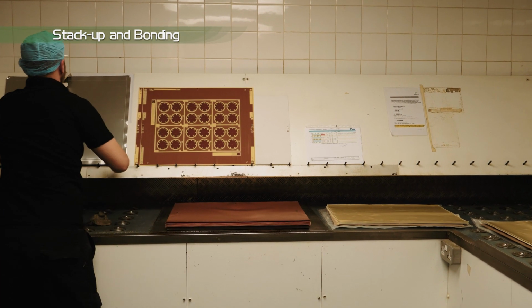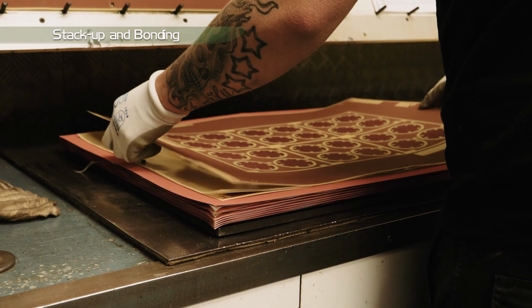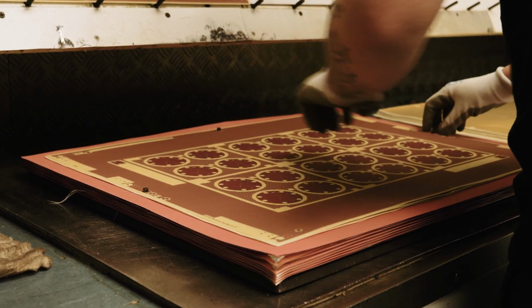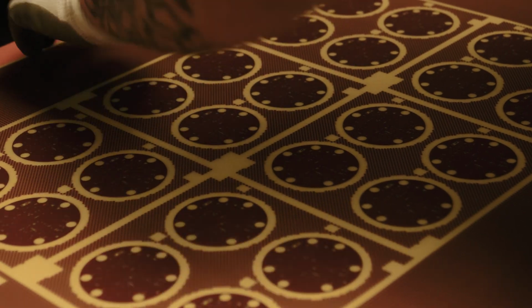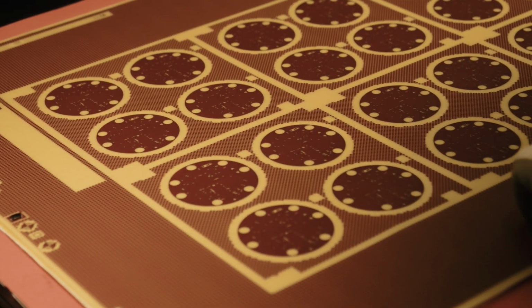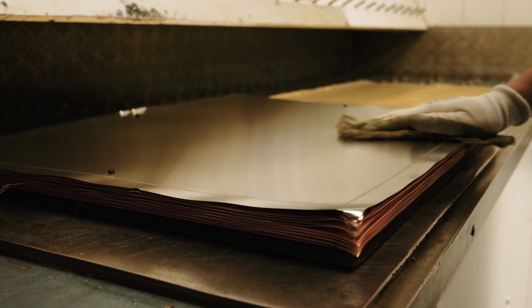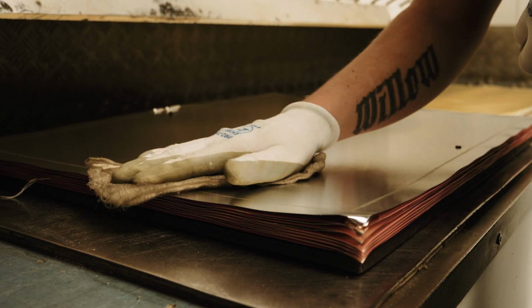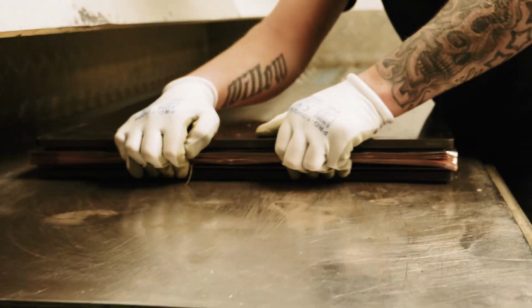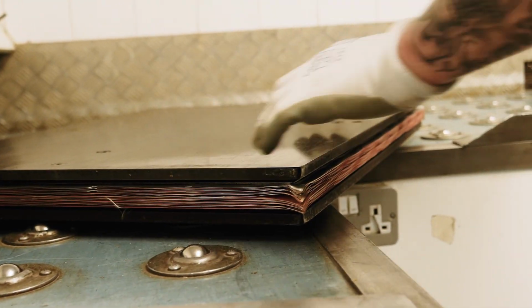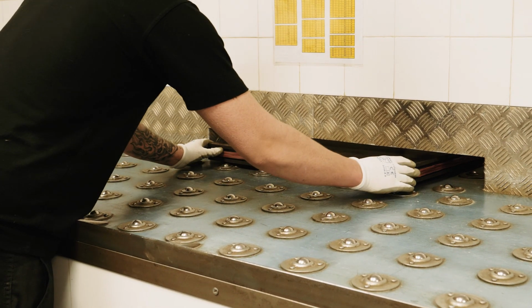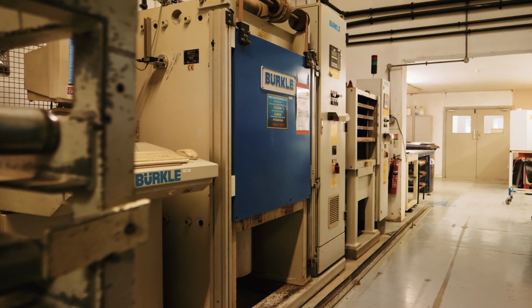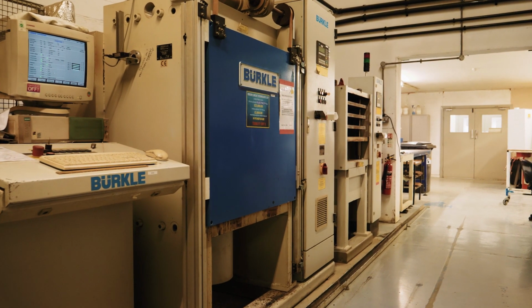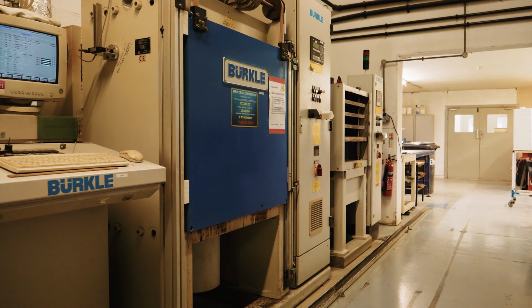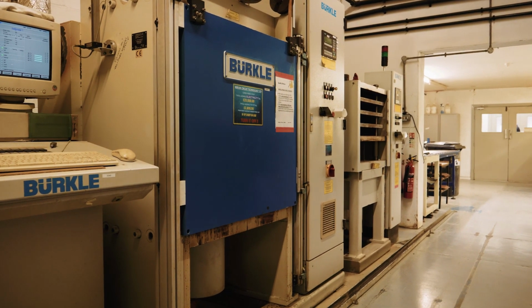The panel is treated using a chemical etch which roughens the surface of the copper to aid adhesion, giving the copper a salmon pink appearance. The inner layer panels are then stacked up with prepreg, a glass fibre sheet impregnated with resin between the layer pairs, and copper foil placed on the outside of the stack in the required order shown on the build sheet. Pressure and heat is applied under a vacuum at specific parameters, which allows the resin in the prepreg to flow and bonds the layers together.